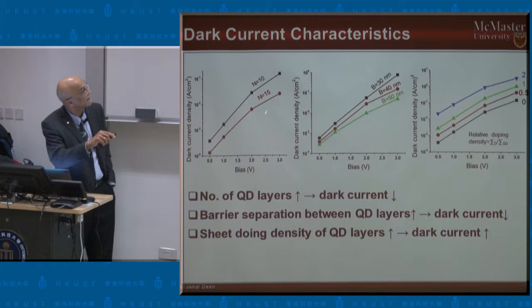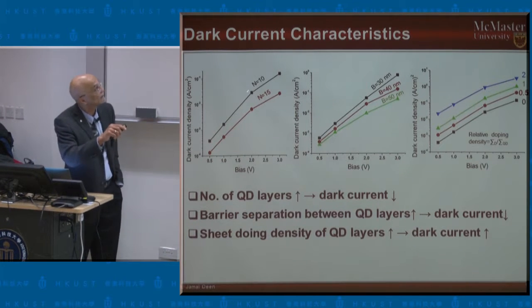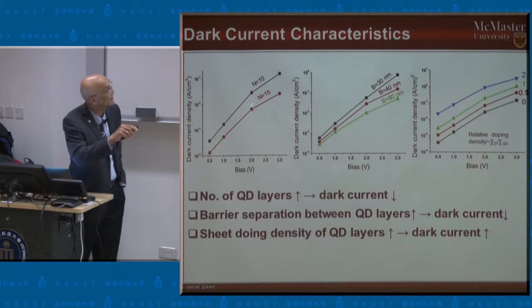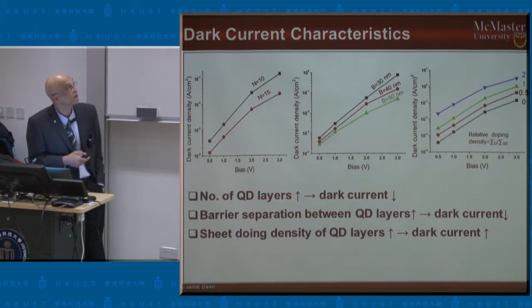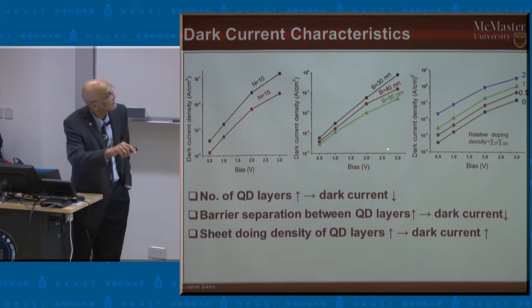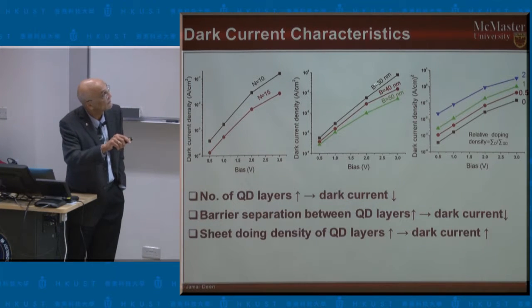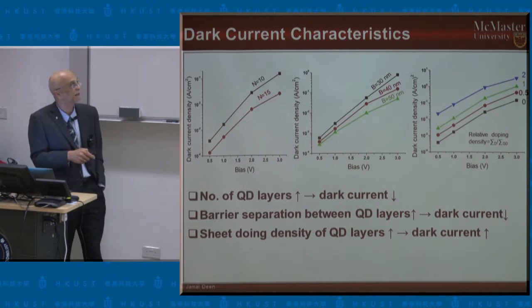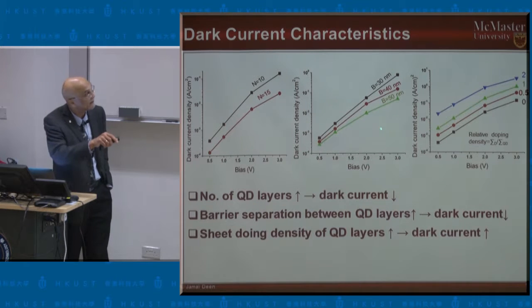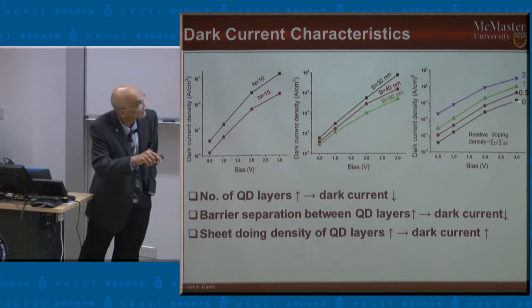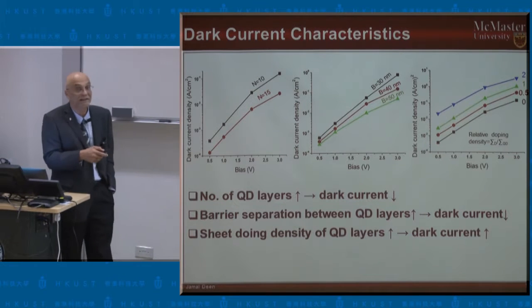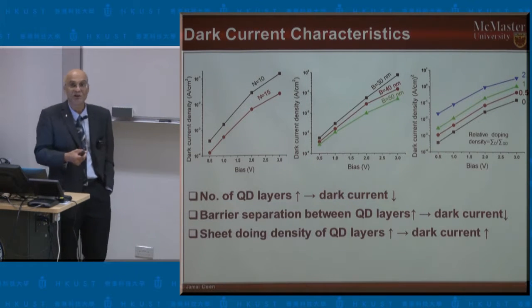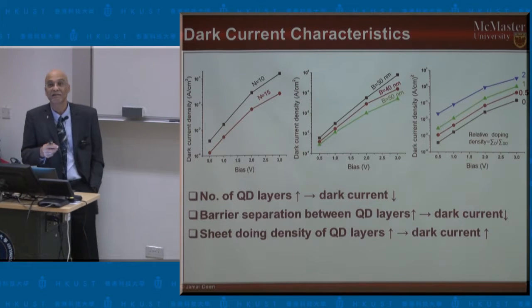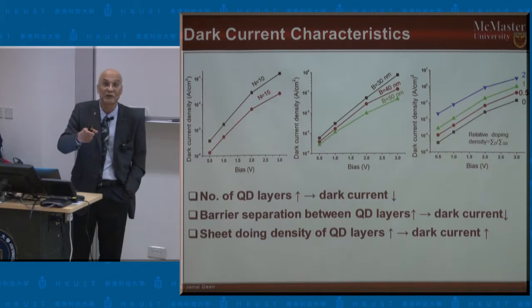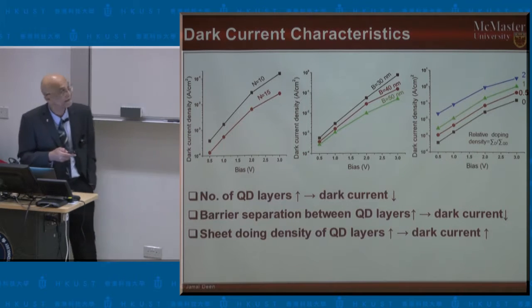We can also look at the number of quantum dot layers. So in this case, we have 10 quantum dot layers, 15 quantum dot layers, and see how it affects the dark current, which would affect the sensitivity. We can look at the barrier, so changing the barrier height from 30 nanometers to 50 nanometers and how it impacts the dark current. So the wider the barrier height, the less the dark current. We can also look at the relative doping densities of the quantum dots and how this affects the performance. So we can look at many different fabrication-related knobs that we can tune to improve the performance characteristics of the device.